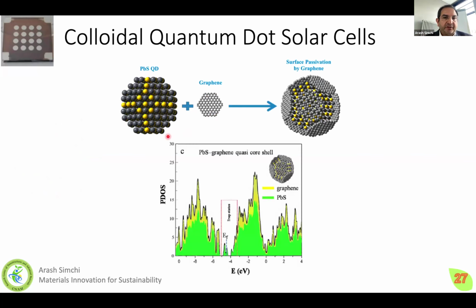However, we used density functional theory calculation, as you see here, a PbS quantum quasi-core shell structure, which we can use. We developed a relatively simple chemical procedure to synthesize PbS quantum dots and then wrap the surface with a layer of graphene. Of course, it's not fully wrapped, but it's mostly wrapped around. And you see here the trap state, and you see that we have a band gap in the system.